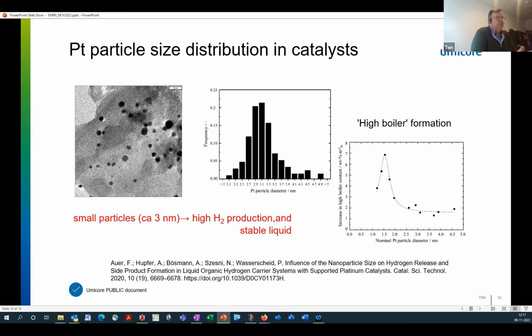So the reaction is running quite well. The liquid is very stable, but during the reaction, you may find that some of the hydrocarbon molecules break, and then they typically will produce heavier molecules, which have a higher boiling point. So this is what the high boiler formation refers to. And if that happens too much, then of course your liquid is not stable. It will have a limitation in the application, and you want to prevent that.